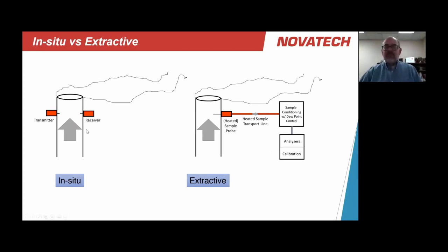If we could do all of our measurements in situ, we probably would. It's simply better from the perspective of being able to do the measurement directly in the process, no sample system. However, we can't do them all in situ. Technologies that can measure in situ are limited, lasers being one of them, for example. And also what's happening in here may preclude our ability to do that measurement in situ. If, for example, this is a stack and there's a fair amount of smoke, then my laser may not work. I may not be able to see from one side to the other. If there's a lot of condensing moisture, I may not be able to do the measurement there. If there are corrosive elements, if the pressure is too high, if the temperature is too high, et cetera, et cetera, et cetera. And so the reality is the vast majority of analyses are done in an extractive fashion, where we control the conditions of the sample so that they suit the analyzer.